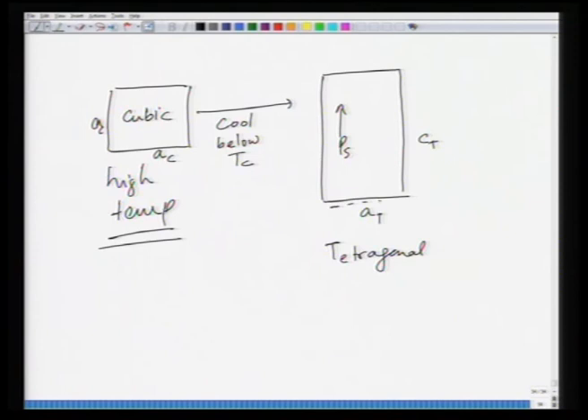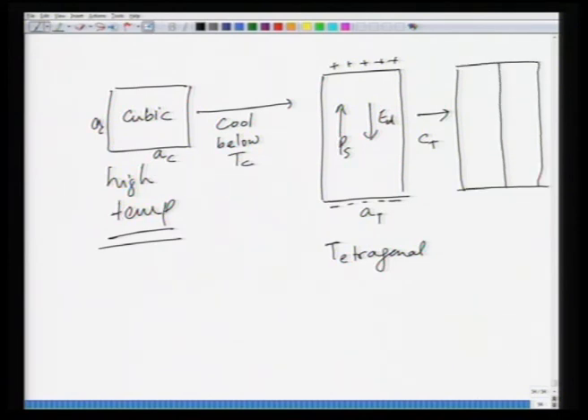So you have a buildup of charges on the faces of the crystal. Correspondingly, you have a depolarizing field, called ED. Now this state, being a monodomain state, is unstable. So what you get instead is polarization in this direction and polarization in this direction.